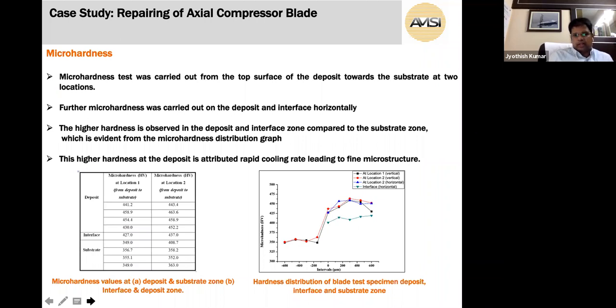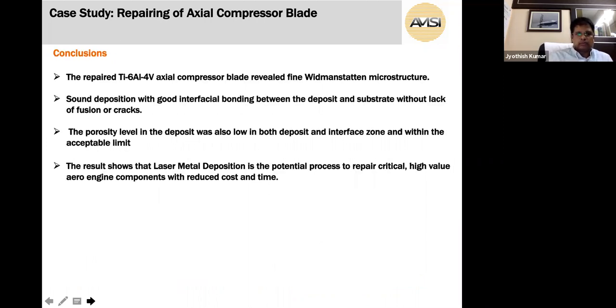Then the interface shows a very good result of porosity and hardness, which is almost closer to the bonding between the base material and the deposition. That is evident that the deposited material is completely melted with the base material, showing very good strength of the repaired blade.